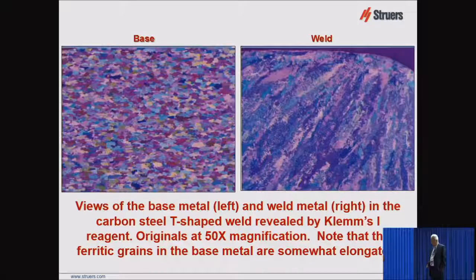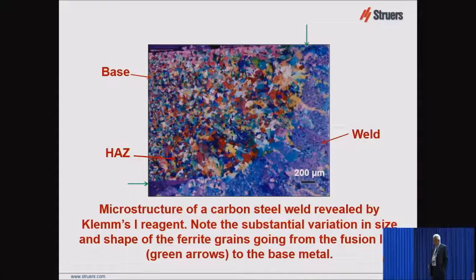Here are higher mag views. This is the base metal, and here's the weld metal. And the color etching really shows the pattern beautifully, and you really can understand what's happening in the weld process much better than anything you do in Nital. And these are both at 50x, so you have more view of the overall structure.